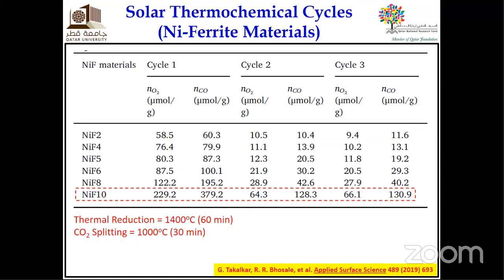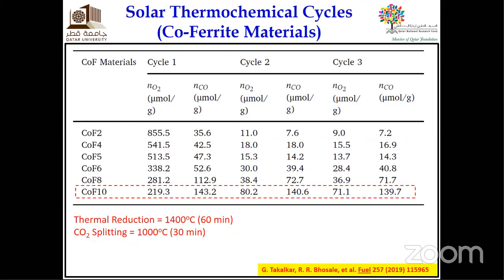Similar to the nickel ferrite, we tested the cobalt ferrite materials, and again we observed that COF10, the last one, has the highest fuel production capacity at the same experimental conditions. So until now, we realized that out of the 6 nickel ferrites and 6 cobalt ferrites we have synthesized, NiFe2O4, which is NiF10, and CoFe2O4, which is COF10, are the best samples. But we have done only 3 cycles.